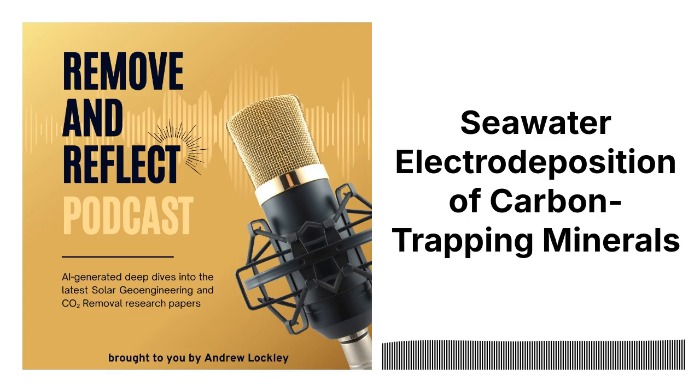Now, let's talk about the carbon sequestration aspect. How much CO2 were they actually able to trap within these minerals? Well, the study confirmed that CO2 is definitely chemically bound within that calcium carbonate structure, and the amount of CO2 captured increased as they applied higher voltages, with the largest amounts being observed under those water reduction reaction conditions. Now, here's something interesting. They also noticed that at higher CO2 flow rates within that WRR regime, they saw a greater proportion of aragonite, which is another crystalline form of calcium carbonate, compared to calcite.